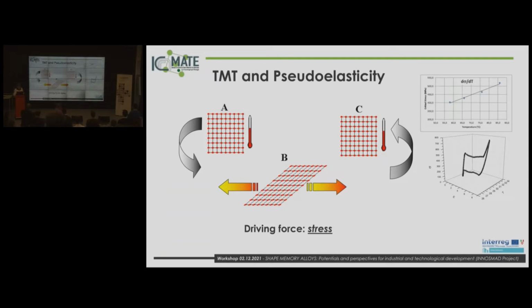This is the typical representation, the typical flag-shaped curve, of this phenomenon in a stress-strain curve. We have the elastic deformation and then the plateau, which corresponds to the transformation to martensite. And then we recover, in an unloading plateau, to the initial austenitic phase. Also in this case, because there are two driving forces, this phenomenon is related to the temperature. Because when we consider this deformation, at different temperatures we have different critical stress. The stress and temperature are in any case correlated. Okay, this is the core of the function of this material. This is the transformation which can work in shape memory effect and in pseudoelastic effect.